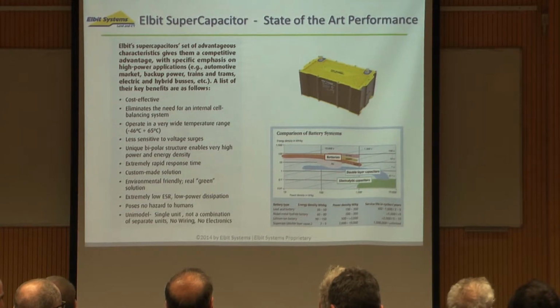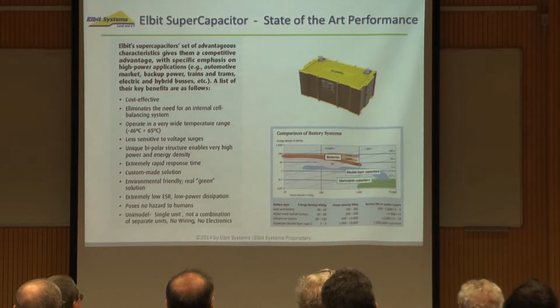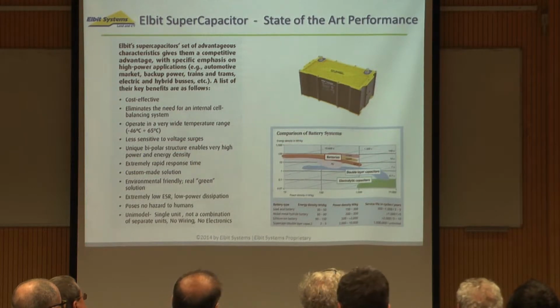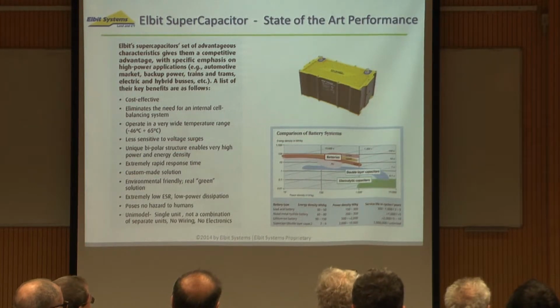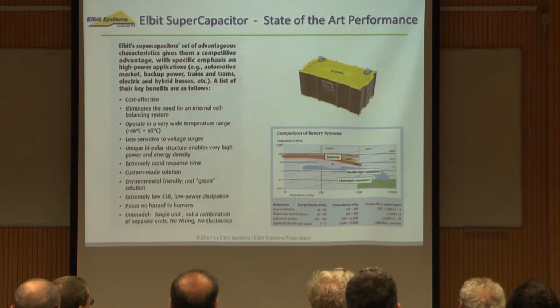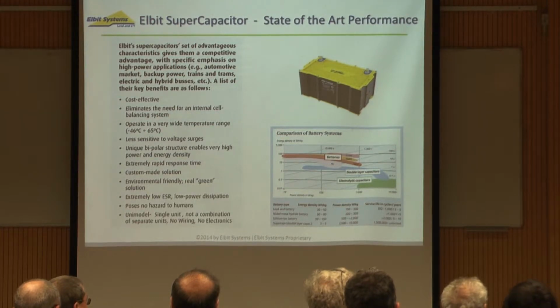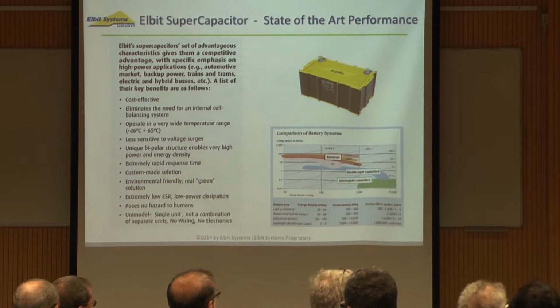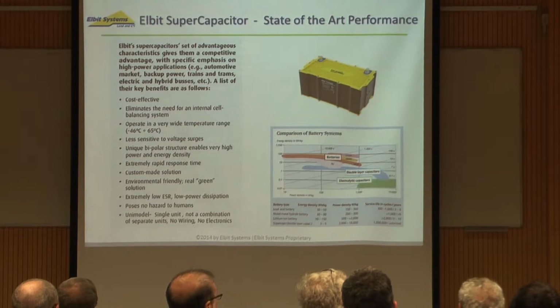supercapacitors. The fact that we use an aqueous electrolyte, meaning the size of the ion is very small, gives us the possibility to reach the best potential of the electrode material, which is usually made of activated carbon with a very large surface area, and those small ions can actually penetrate and access each and every pore of this activated carbon, which means we can get maximal capacitance.